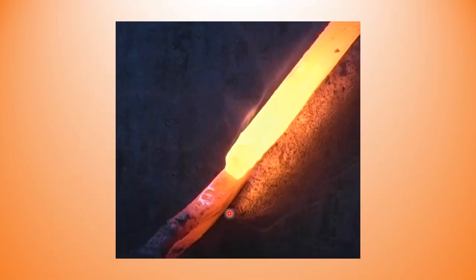Here are two pieces heated to different colors or different welding heats. Notice this looks wet, this looks wet, but they're not the same temperature. These two pieces were initially welded but then later they failed. You want to make sure that both pieces are the same color when you conduct your weld.